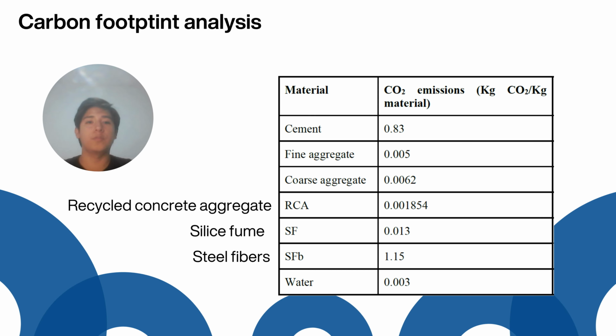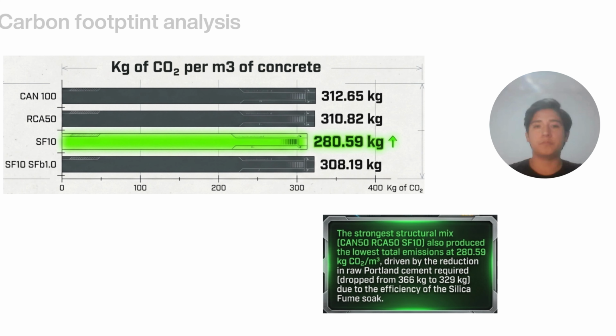In addition to improving strength, the proposed mixtures demonstrated environmental benefits. A carbon footprint analysis was performed using emission factors associated with all the materials. See on the presented table that the RCA emission factor is lower than the coarse aggregate factor, and also see that the silica fume emission factor is lower than the cement one.